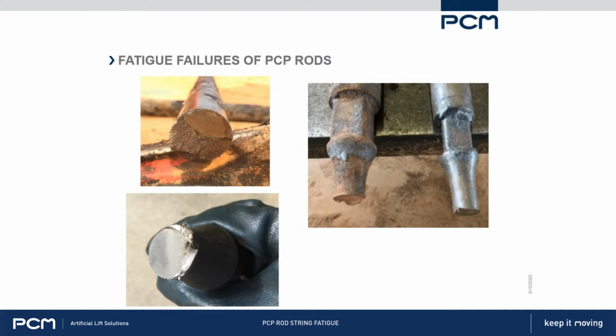Going down below it here, the smooth surface is very, very large. In the analysis we did for this well, it showed that the rod was only at about 12% of its capacity. So that's why you can see that there's only about 12% of the rod left that had the final failure on this rough surface here.